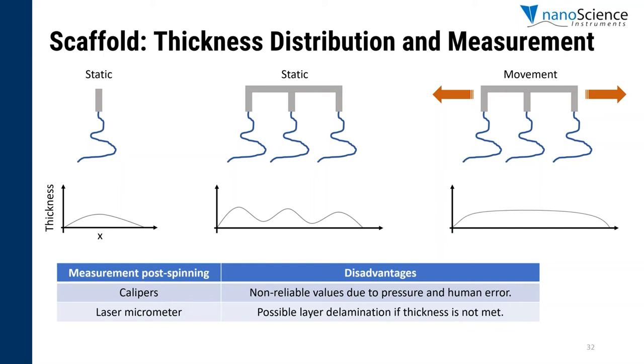Meanwhile, emitter movement can be implemented to get a better thickness profile, and then you can get a more homogeneous thickness. For example, this is really important for filtration applications because you really want a uniform thickness all around the sample to maximize filtration performance. But then if you achieve a really uniform thickness, you then need to make sure that the thickness is really well controlled all around the whole sample.